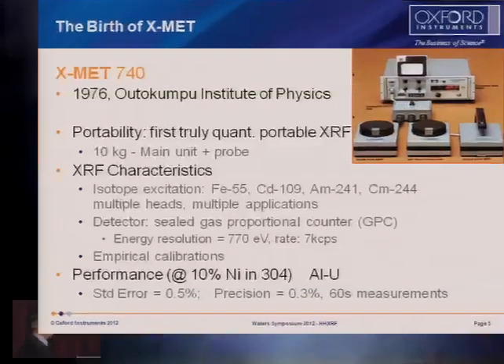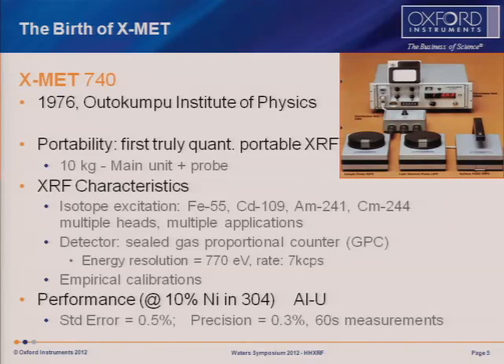And the detector: silicon pin diodes had not arrived then, but gas proportional counters were developed very heavily by Heikki Sipilä, who's been involved right through the development of gas proportional counters in X-ray spectrometry and in fact in space exploration. The energy resolution was a little bit better than the original pins of Alan Huber as reported shortly ago, but not much better. It required a huge amount of empirical calibration to make them work for the applications. But my bellwether, if you like, for the performance is that of nickel in 304 stainless at about 10%. The standard error of 0.5% was particularly attractive, but more so was the precision, and in only 60 seconds, and on site.